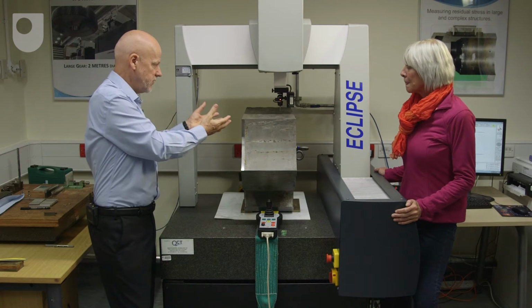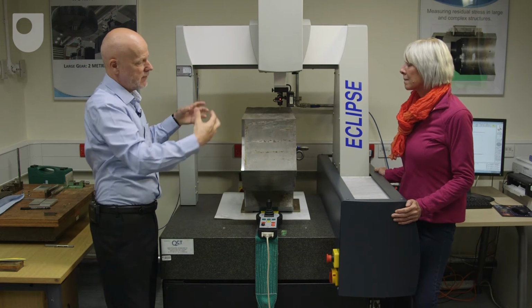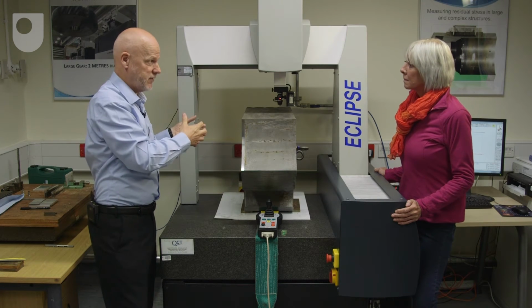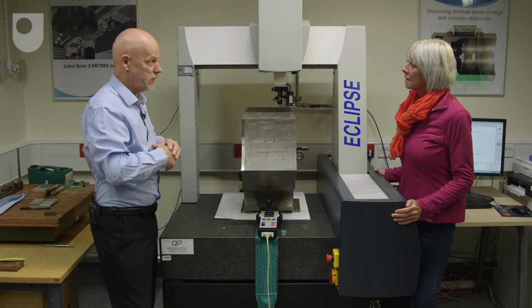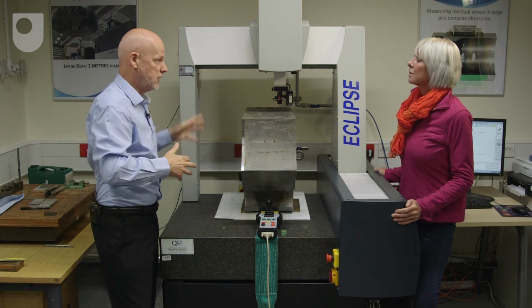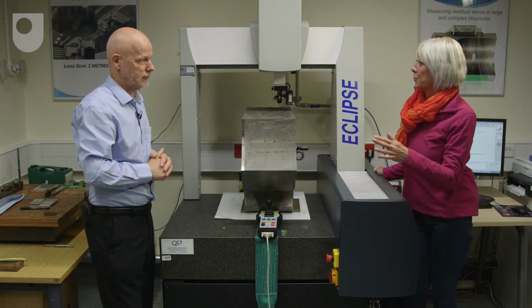Well, it will tell in this component what that stress state is, and they will then compare it with some predictive models of what they think is there. Right. And then that will help them to understand the reasons for the failure of this wheel. So presumably your research is useful in industry? Well, this technique which we implement here is quite cheap, it's quite quick, and it gives you a map of the stresses. And so industry are very interested in measurements using this method. So much so that we've had many requests for measurements, and we've set up an internal business unit providing a commercial measurement service. So that's your research, and that's the work that you do for industry.